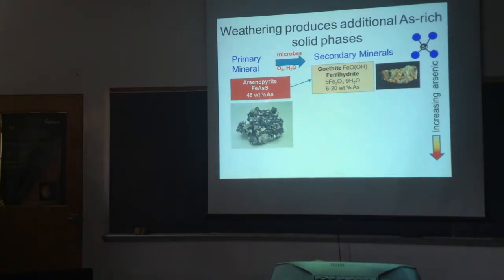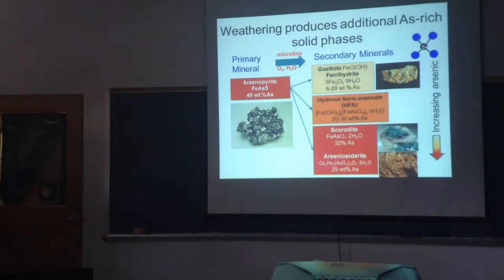When you get to arsenopyrite, the mineral I mentioned earlier, it actually has arsenic right in its structure in equal molar quantity to the sulfur and the iron, or 46 weight percent altogether. You can get ferrihydrite with up to 20 weight percent arsenic. We'll still call that HFO. There's a kind of gradation into stuff with even more than 20 weight percent arsenic. We call that HFA, hydrous ferric arsenate. And it's somewhat of a continuum here. It's just an arbitrary distinction that's been made in the literature. When the iron arsenic ratio reaches a certain point, we start calling it HFA instead of HFO. And I'll show you some diagrams that make that a little more clear.